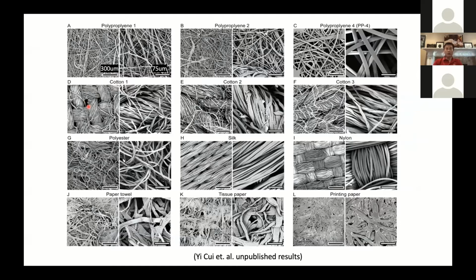And then 2 and 3, the same scale bar on the left, you don't see those big holes right there. It consists of this fiber, but you don't see these big holes. So it's kind of the weaving, it's tighter, but it still has some small holes to let the gas, the air, go through. That's why 2 and 3, the quality factor is higher. You look at polyester, it has all these small holes right there, no big holes. Quality factor is reasonable. Polyester is great. Silk, this weaving is too dense, and nylon, this weaving is too dense, really too dense. Remember, I told you the nylon air pressure drop is too high. Its quality factor is low.